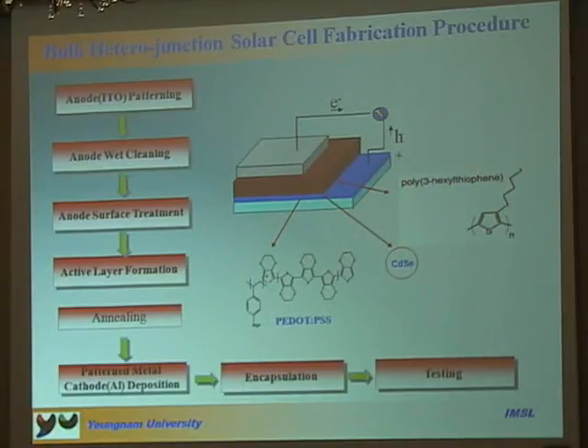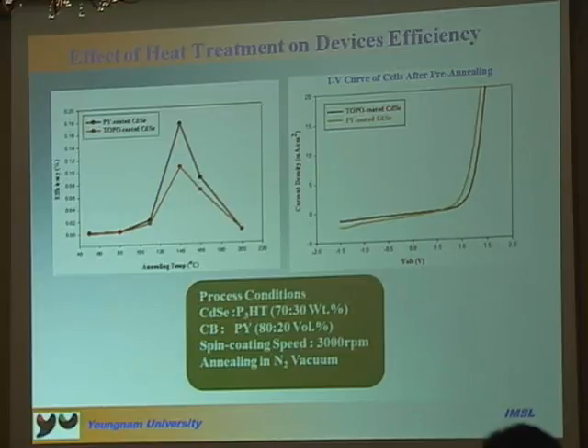The bulk heterojunction solar cell is also fabricated by this procedure. First, ITO patterning, wet cleaning, surface treatment with plasma, active layer deposition, annealing, and aluminum deposition, encapsulation, and finally testing with a solar simulator. After investigating the heat treatment, we get some results. In the left side figure, we can see efficiency depending on annealing temperature. At 140 degrees, we get maximum efficiency.